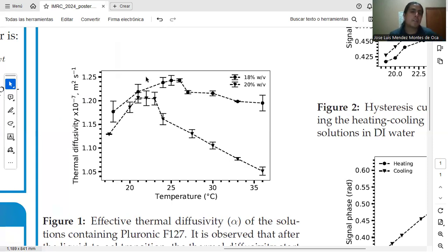And it is observed that before the transition, as the temperature increases, the thermal diffusivity of the liquid also increases, quite similar to the behavior of other liquids such as water or alcohol. But after the transition, when the material is a gel, as the temperature increases, the thermal diffusivity decreases. We regard that this unexpected behavior is because as the temperature is increased, the entanglement between the polymeric chains is also increased, and the thermal transport across the material is decreased.